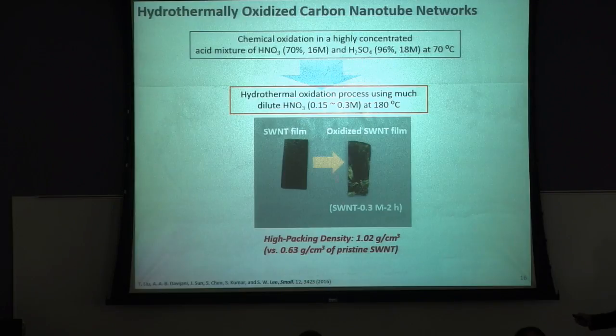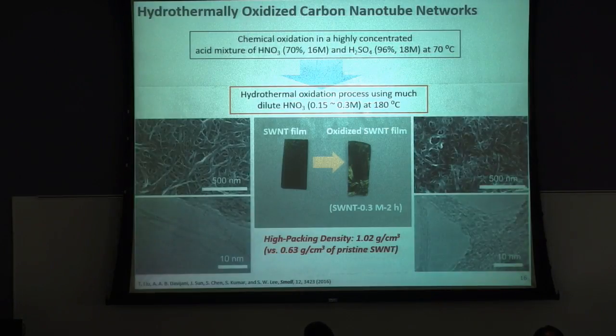We first prepare a single-walled carbon nanotube film. Then we put this film into a closed vessel with this dilute nitric acid solution, and we just heat it. Then we can create oxygen radicals that attack the carbon nanotubes, so we can oxidize this single-walled carbon nanotube film. If we see the morphology of the single-walled carbon nanotubes, as you can see again, the surface of these nanotubes becomes roughened after the oxidation process.